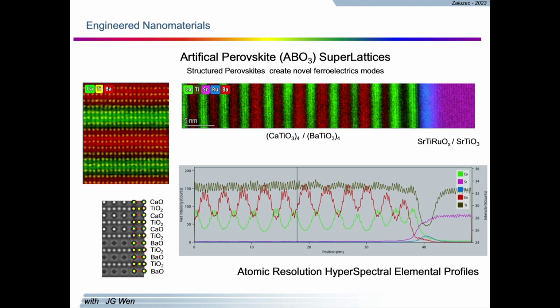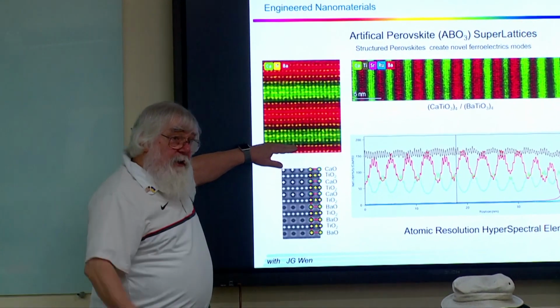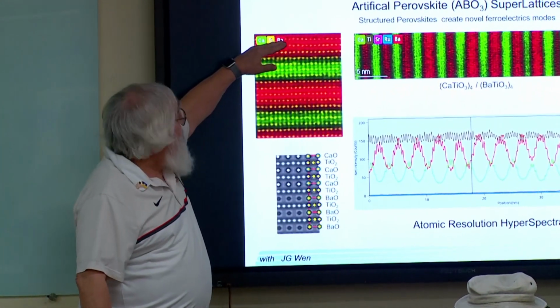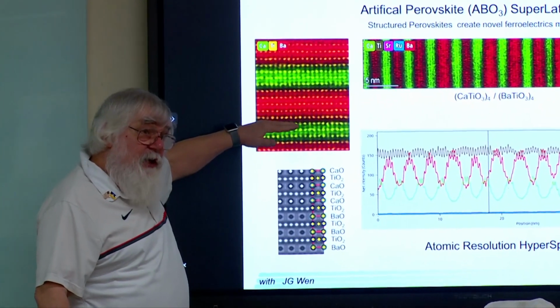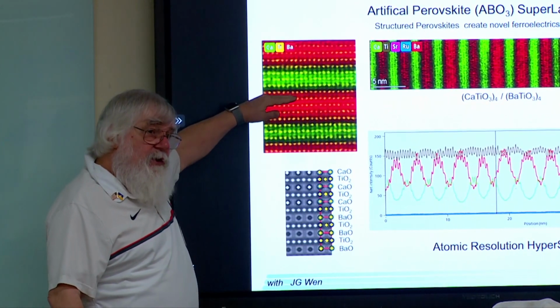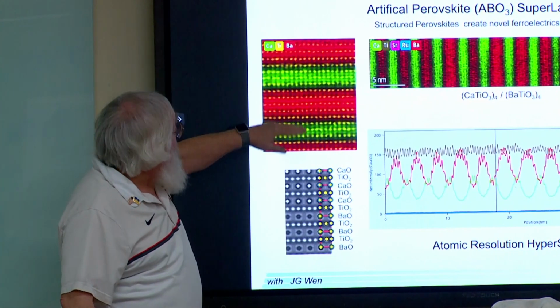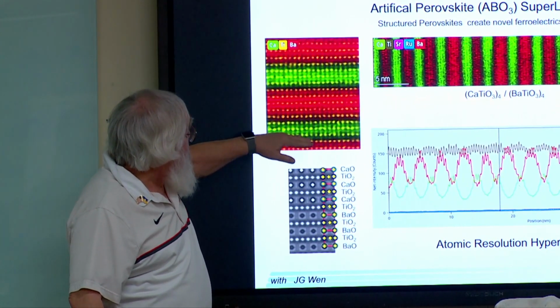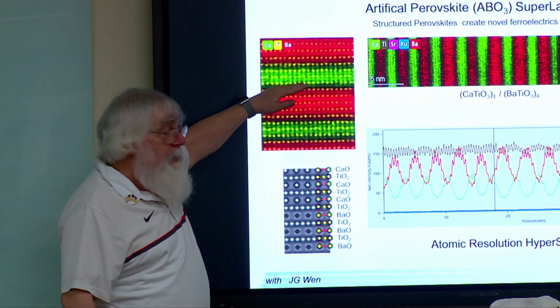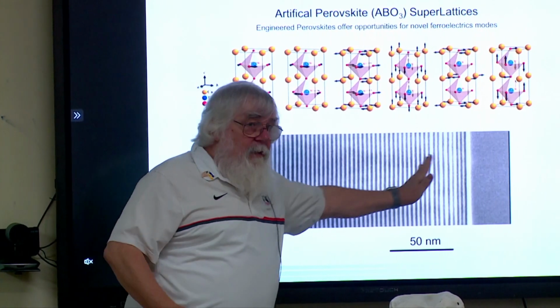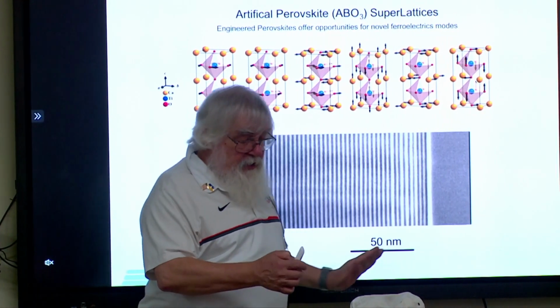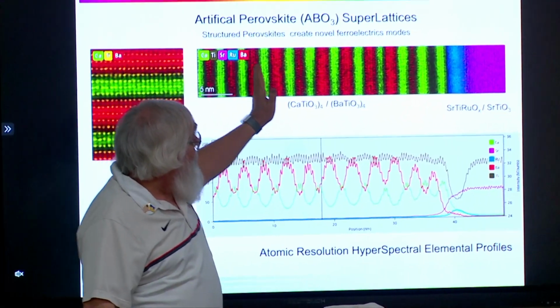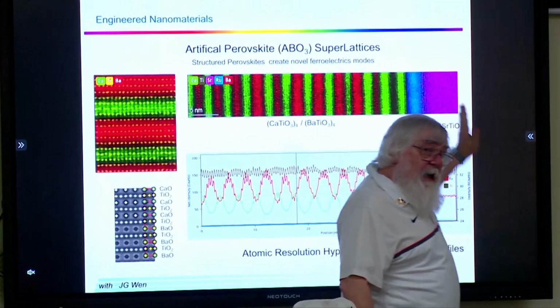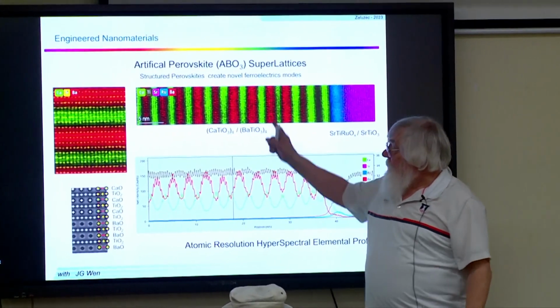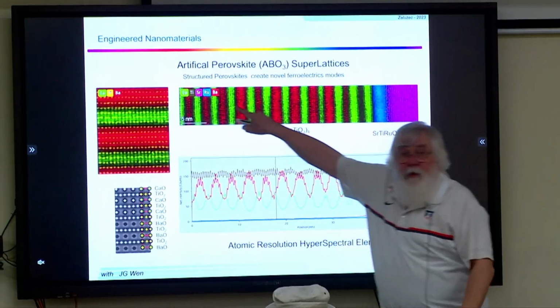The nice thing that we can do today is that modern analytical instruments can actually measure that. This is a color-coded image, and this is actually an elemental composition distribution. The green is the calcium, the yellow is the titanium, and the red is the barium. When we looked across that very long strip, we noticed there are changes across there. If I go across it, I can map out the elemental changes or distribution across that. And this is a line trace across here.